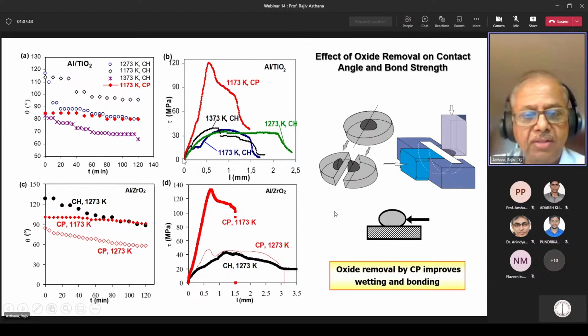So this is the bond strength versus the displacement of the droplet during this kind of a test. And these are the contact angle data with time for contact heating systems, and the red one is for squeezing the droplet out. So because we were able to remove the oxide skin, we got very high bond strength in the system, even at 1173 Kelvin wettability test. And even at 1373 Kelvin, contact heating did not give you that level of bond strength because the contact was not very good. Interference from oxide caused this problem.